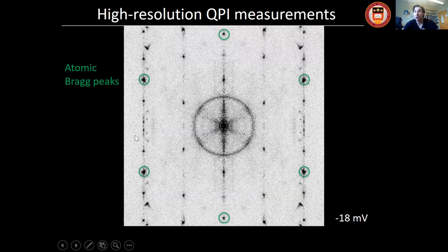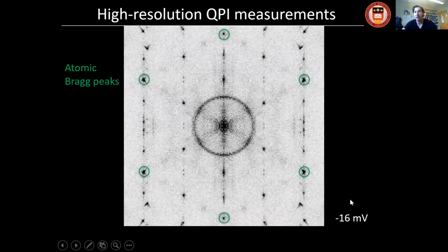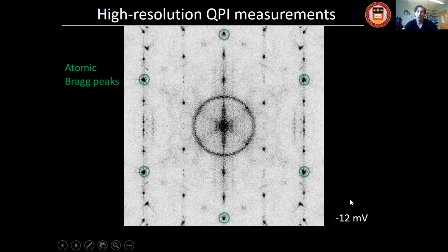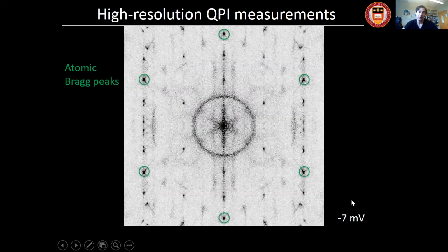So given the audience, I want to show a little bit about how these QPI measurements actually evolve as a function of energy. So this is minus 18 millivolts. We focus on, to get this k-space resolution, probably about a 100 by 100 nanometer, flat, clean-ish region of the space, and then just change the energy and take the Fourier transforms of the STM dI/dV maps. So this is minus 18, and then I'm going to increase the energy, trying to click this fairly uniformly.